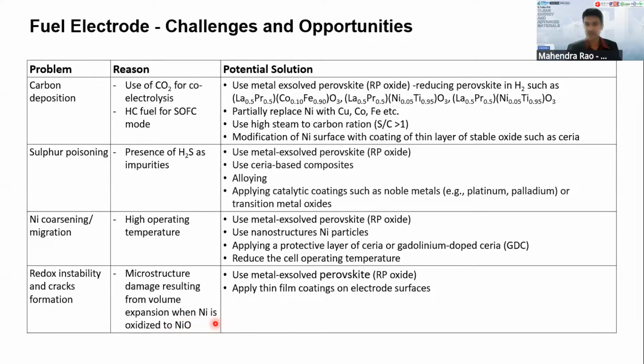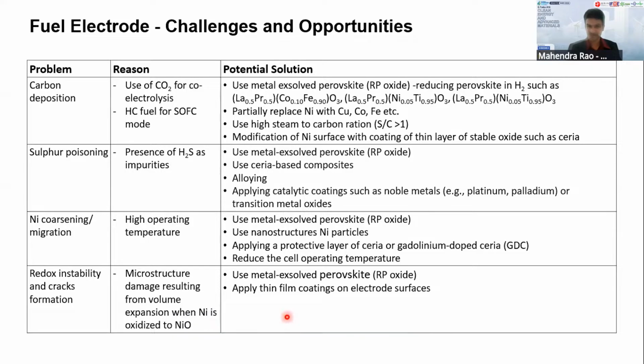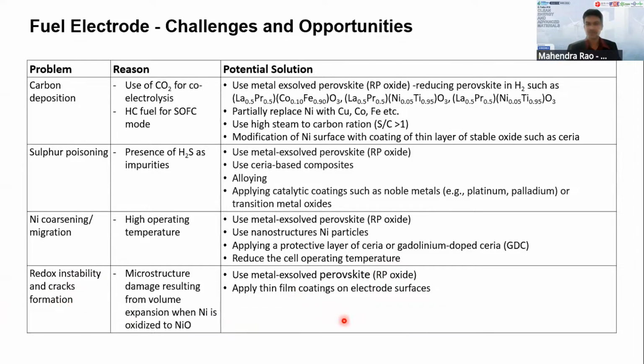And then we know the redox instability is another issue, especially for the anode supported cell. So we know the microstructure damage is due to the volume expansion when nickel is oxidized to nickel oxide. So again, people are looking at using the perovskite as a possible solution to mitigate this issue, and then thin film coating, for example, to avoid the oxidation of the nickel. So these are common challenges and opportunities that we need to consider when we're designing materials or proposing some materials for the potential application, because these are common interests of most of the industries.